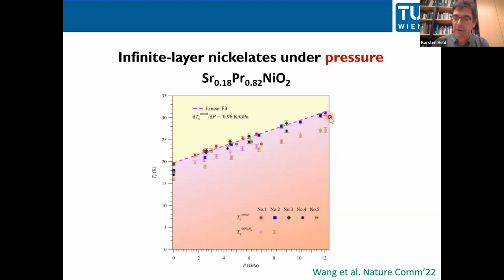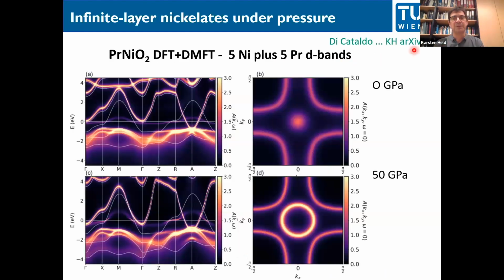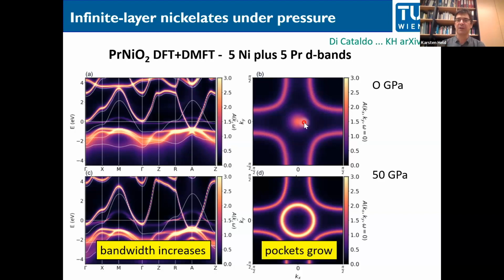And so in a most recent archive paper, we looked into the pressure. Again, we start doing a DMFT calculation without pressure and with pressure. That is now the praseodymium, because the experiment was praseodymium. And there are 2 effects with pressure. One is what you expected. So this width here increases, as you can clearly see. And with the increase of the DFT width, you also see that the DMFT band gets more weight. So the quasi-particle weight increases, and the dispersion also in DMFT gets larger. But there's a second point, that these pockets grow quite substantially under pressure. Without pressure, this gamma pocket is essentially 0, and with pressure, you get some larger pockets.